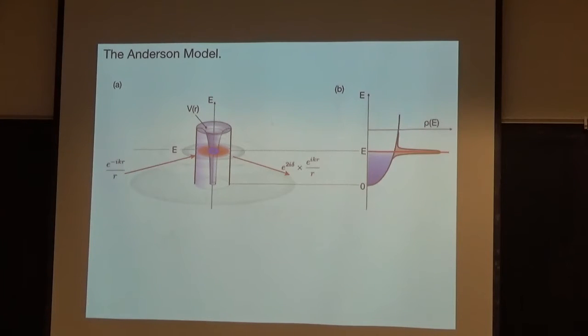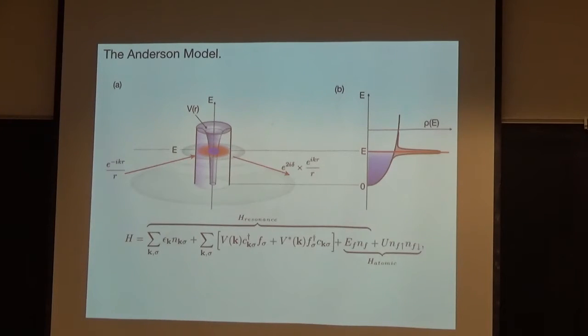However, this then leads to a cascading sequence of models that capture some aspect, but not all aspects, of physics. And one model that captures a lot of the basic physics, but is not simplified enough for our purposes, is the Anderson model. The Anderson model is kind of like the alpha particle picture of electronic systems. The electrons in the d states, or the f states, of an Anderson model are localized inside an atomic potential well, but they can resonate with the conduction electrons. They can tunnel through that potential well into the conduction sea, and that tunneling is described by the hybridization. In this case, I've assumed it's an f electron here. And then in such a simple model, there's also a repulsive U between two f electrons in a given orbital. This is the basic Anderson model.